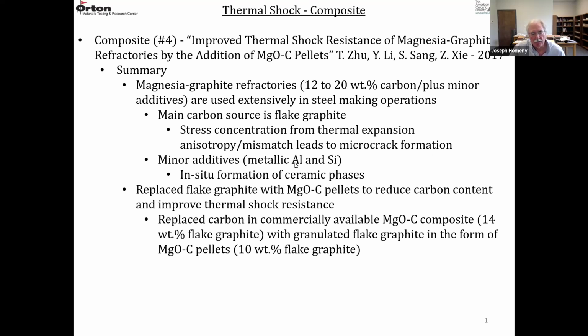And the minor additives are usually metallic aluminum and silicon, and they form ceramic phases in the refractory, usually in conjunction with oxygen. They're oxygen getters. So they remove the oxygen before it can react with the carbon. So in this study, they replaced flake graphite with MgO carbon pellets in order to reduce the carbon content and improve the thermal shock resistance.